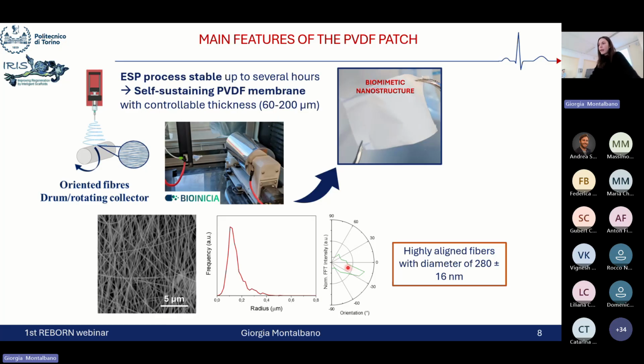So thanks to the optimization of the process and the study of the combination of the different process parameters, we could end with a very stable process over time that led us to the design of a self-sustaining PVDF membrane. As you can see here from the images, these membranes were characterized by highly aligned fibers with an average diameter of about 280 nanometers, so obtaining a more biomimetic construct resembling the characteristics of the